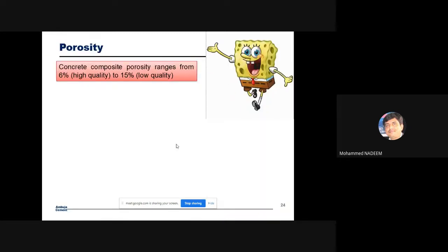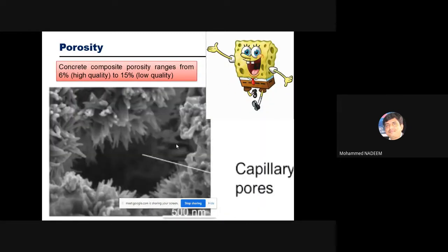So we just saw the porosity, again the same picture taken in a closer view of capillary pores in concrete, which looks like this. In normal concrete, depending upon the quality, the porosity is in the range of 6% to 15%. Ordinary concrete has a water cement ratio of say 0.55, and in traditional concrete, people normally add water in the tune of 30 liters, 35 liters, maybe a water cement ratio of more than 0.6, 0.65. In that case, the porosity will be around 15%.